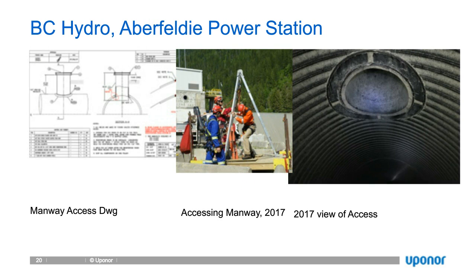There are only two access locations to the pipeline, and they're both near the limits of the polyethylene pipe. The design drawings for the access point are on the left. In the middle, you see us accessing through the manway, and the picture on the right is the last of the manhole just before we get to the steel portion. And there was no evidence of either ductile creep or formation of cracks at these manway access locations.